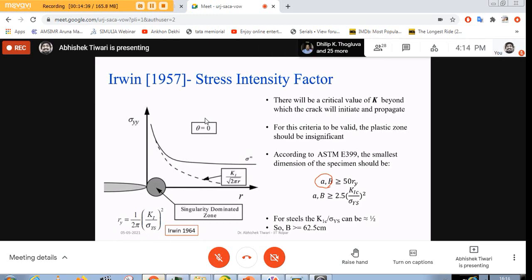And this causes problems for ductile materials like steel. Steel is a material which is used in the maximum amount in structural components. And for steels, you have to test a specimen which is at least 2 feet thick, so 62.5 centimeters. And you can imagine if you have a sample which is 2 feet thick, what kind of load you will have to apply to first handle it and then break it and then handle the broken sample. So this is not so good for testing ductile materials.